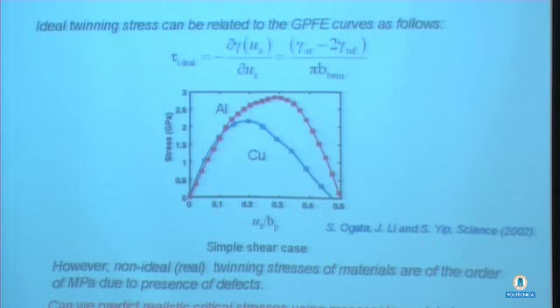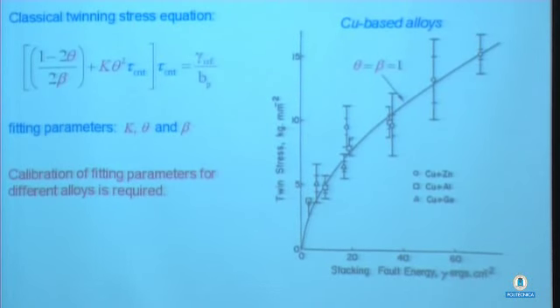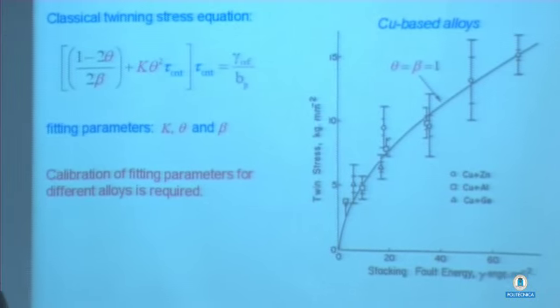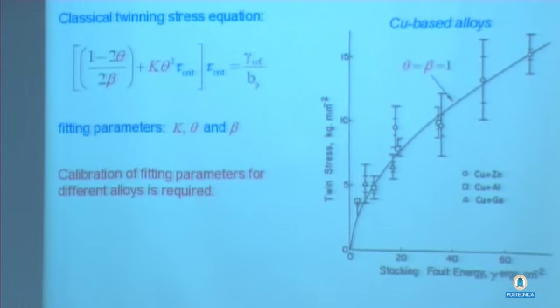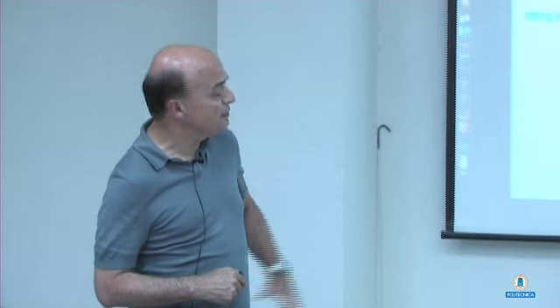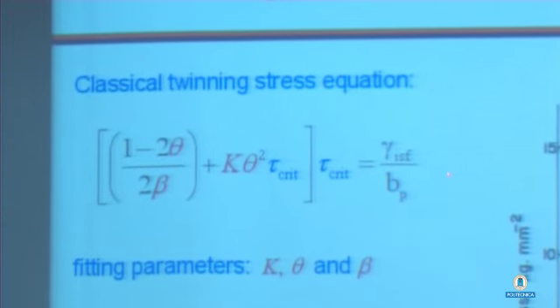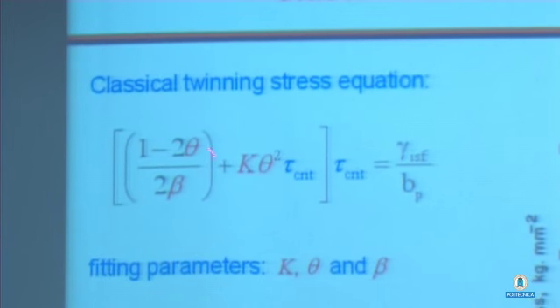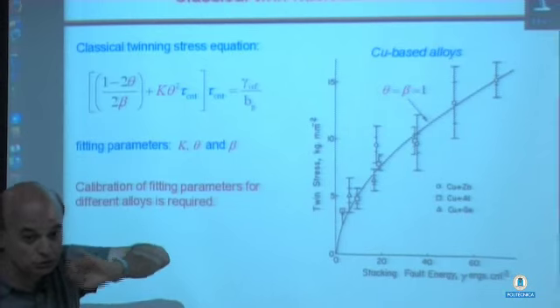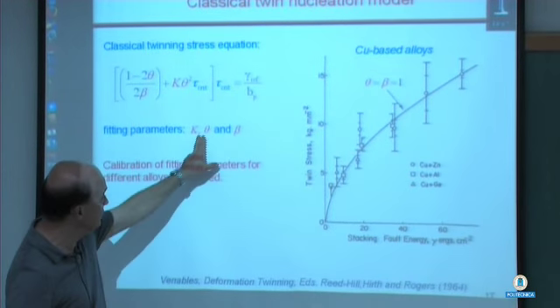Can we predict realistic twinning stresses? Because if you look at twinning stresses for these pure metals, they are of the order of megapascals, not gigapascals. Okay, this is gigapascals. So there are some simple models out there. I shouldn't say theories, but there are some simple models out there, and they go back to the 1960s, and they all say the critical stress for twinning is proportional to gamma ISF, the intrinsic stacking fault energy. There are some constants they have, theta, beta, k. These are constants. Of course, we're trying to determine it without any constants.